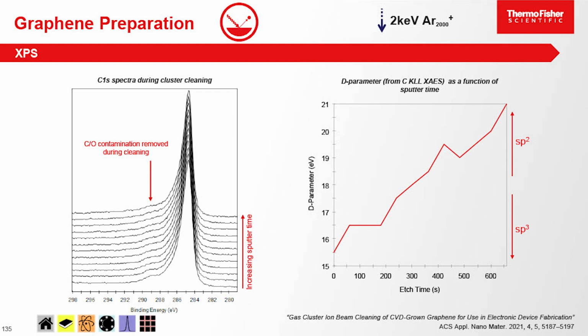And over on this side, we're measuring something we call the D parameter. And this is just a measure of the sp2, sp3 carbon chemistry. So sp3 is diamond, basically. sp2 is graphene, graphite. So the more sp2 we have, the more we have our graphene surface. That's what we want. It's quite a simple measure to do. We just measure the carbon KLL Auger feature, which is quite a bit higher in binding energy than the core level, and differentiate it, and the software automatically does the measurement. So we can just plot this out from our depth profile.